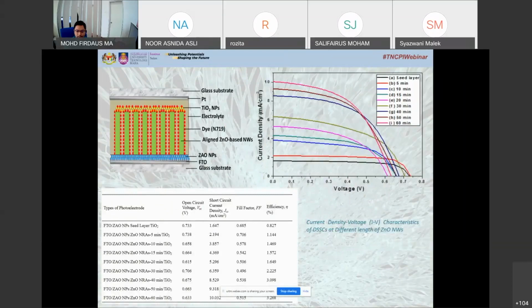Okay, here are some of the results. Here is the deposition of zinc oxide by varying the time. So you can see that by varying the time, as shown before, the length of the nanowires will be increased. So you can see the efficiency of the solar cell that has been fabricated. The efficiency, this one you can compare. This one is without nanowire. This one is the structure that we're using.